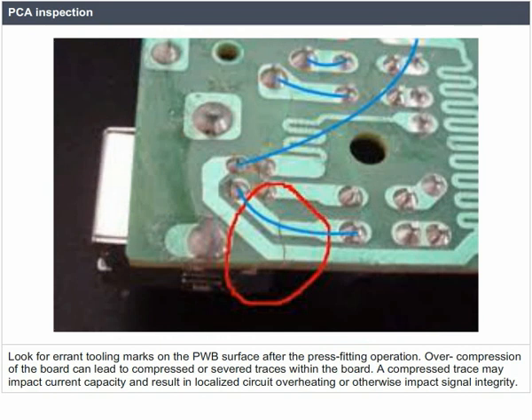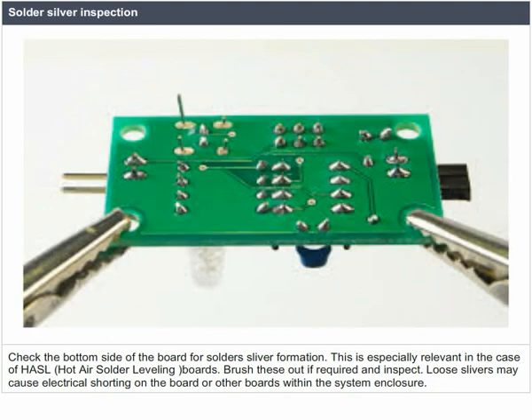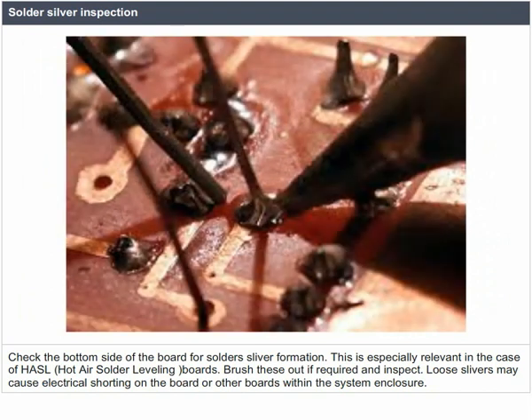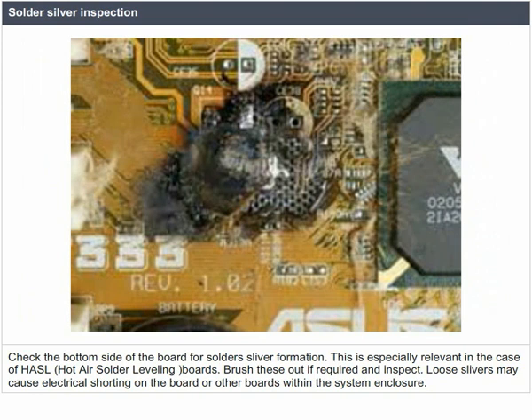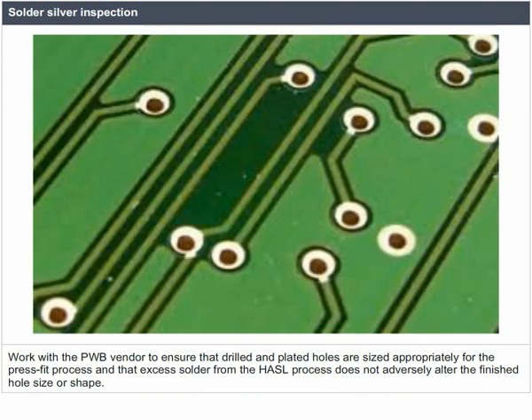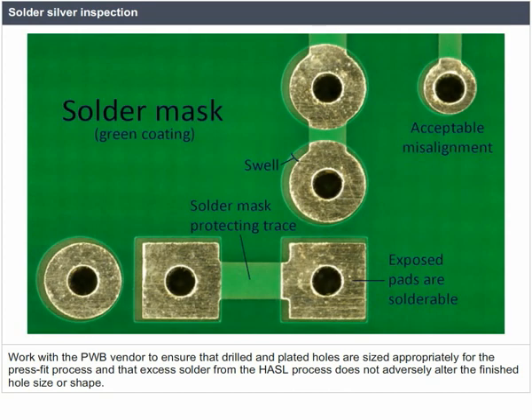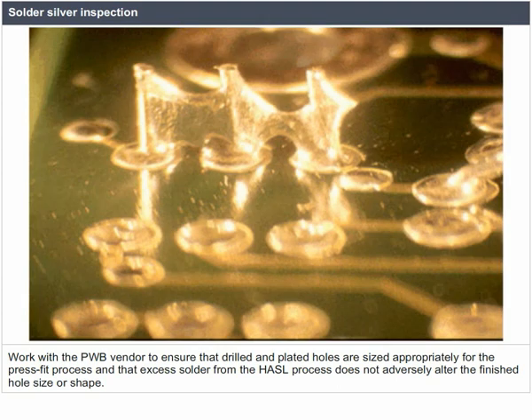Solder sliver inspection. Check the bottom side of the board for solder sliver formation. This is especially relevant in the case of HASL, hot air solder leveling, boards. Brush these out if required and inspect. Loose slivers may cause electrical shorting on the board or other boards within the system enclosure. Work with the PWB vendor to ensure that drilled and plated holes are sized appropriately for the press fit process and that excess solder from the HASL process does not adversely alter the finished hole size or shape.